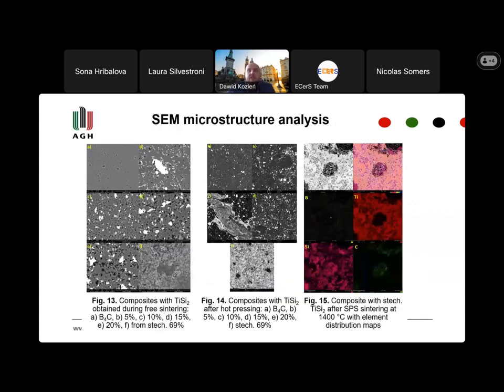And after that, we check the microstructure. Of course, we can see that we have worse microstructure in the method like free sintering. We have more porosity, and it's obviously because some carbon from the boron carbide is removed like carbon dioxide. In the HP method, we have better microstructure, and the same situation with the SPS method. But in the SPS method, you can see something like that.